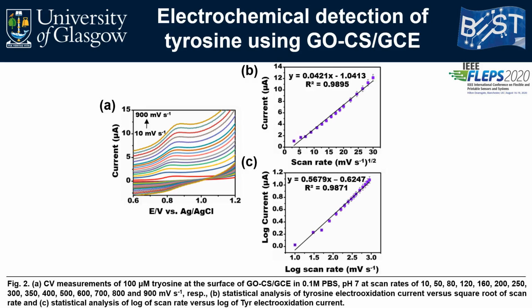The effect of scanning speed on the electrochemical oxidation of tyrosine at the graphene oxide Chitosan glassy carbon electrode surface was studied at various scan rates ranging from 10 to 900 millivolts per second in the presence of 100 micromolar tyrosine. Figure 2a shows an increase in oxidation current with an increase in scan rate and a positive shift in oxidation potential from 0.84 volts to 0.86 volts, which is typical of irreversible diffusion reactions.